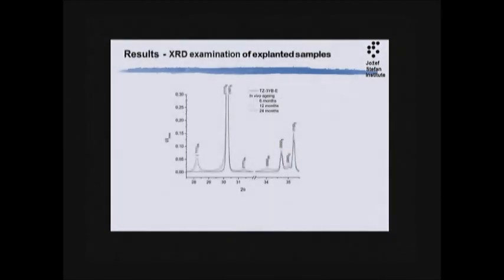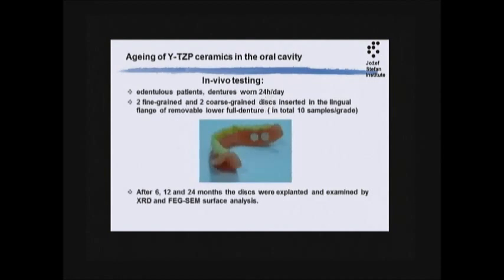So the reason why we have chosen the 2 materials, they were the finer grained one and the coarser grained one. The finer grained size was just below 0.4 microns, which is, according to the standard, the grain size still allowed. The other one was 0.45 or 0.46 microns. That's above the value recommended by the standard. I was curious to know whether this makes sense or not and how much.